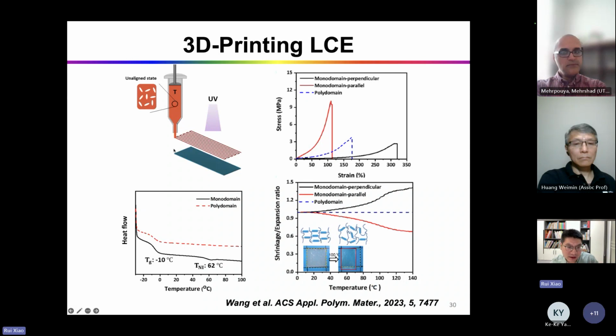And if you increase the temperature of the substrate, the mesogens go from the oriented direction immediately to a random direction. So it can print either monodomain or polydomain LCEs—basically you can control this through the temperature of the substrate.